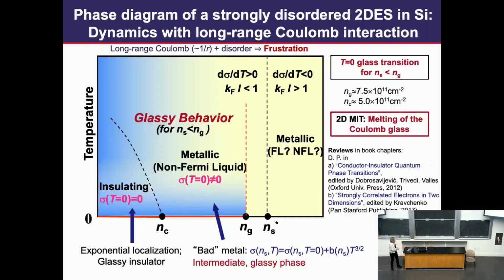So this is a sketch that includes the results on the dynamics. We found that there is a well-defined glass transition density, below which there is a glass transition at zero temperature at all of these densities. So we have this glassy insulator, and an intermediate bad metal glassy phase in this system. All the measurements are consistent with each other, and ultimately the reason this is glassy is because you have frustration due to the presence of a long-range Coulomb interaction and disorder.